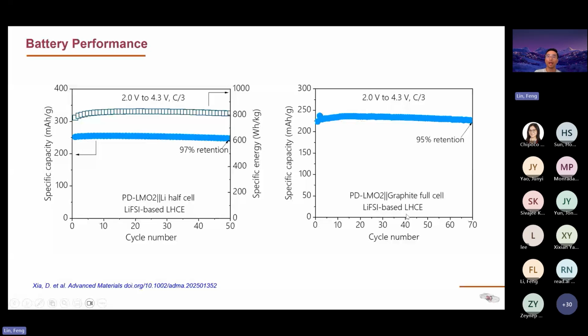The reason we use localized high concentration electrolyte is to mitigate a lot of issues with manganese-rich cathodes, such as manganese dissolution. The localized high concentration electrolyte can help us at least mitigate some of the dissolution problems. So this is our perspective on